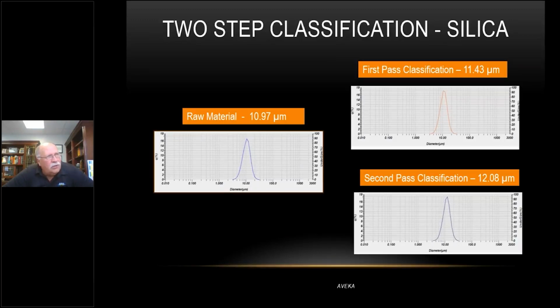This first one is a two-step classification of silica. And you can see the raw material that we received is about 11 microns. So it's a pretty tight distribution to start with. But once again, there was a few too many fines in the system, and our customer wanted us to take the fines out, but really maximize the amount of yield that we have. And so this is an interesting problem. Rather than cutting into the middle of the distribution, we're basically going to nibble at the edges. We're going to take out just as few amount of material as possible.